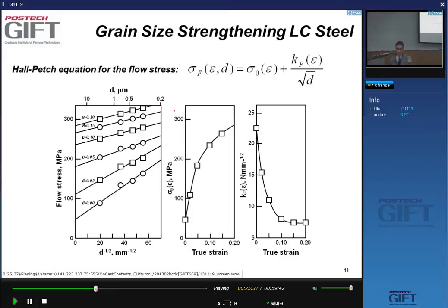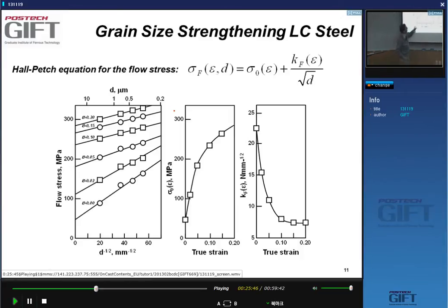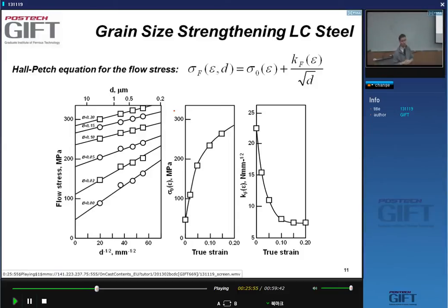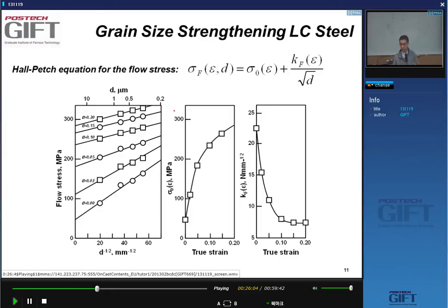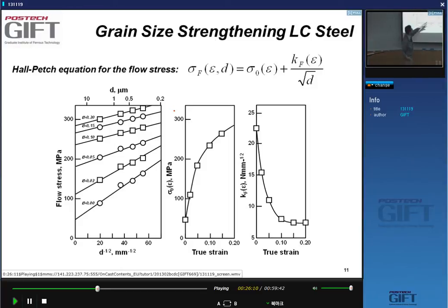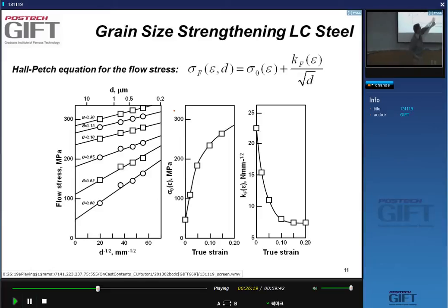The two constants — sigma zero and the Hall-Petch slope Kf — are actually not constants; they are strain-dependent parameters. In general, sigma zero will increase with deformation, while the K value decreases as the curves become flatter. The important message is these parameters are not constants. When you use them for strength calculations, be very careful: are you using this equation to calculate the effect of grain size on yield strength, or on flow strength?